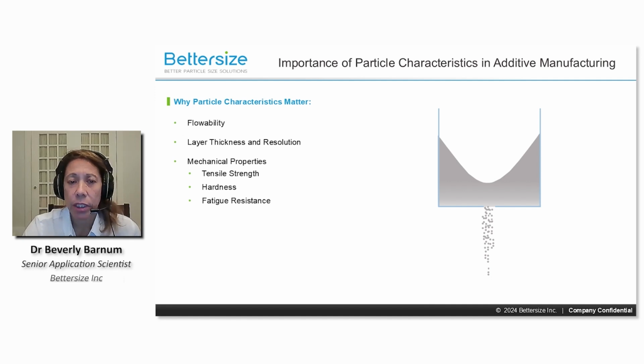And fatigue resistance is the property of a material that allows it to resist breaking down over time under the influence of changing workloads. Additive manufacturing parts are typically less resistant to fatigue than conventionally fabricated parts, but this can be overcome. Additive manufacturing parts can have defects like lack of fusion, gas pores, surface roughness, and grain boundaries that can make them less resistant to fatigue. And the material microstructures, including its grain size and phase distribution, affect the fatigue resistance. Smaller grains can better absorb and dissipate energy from loading, while certain phases can reduce crack propagation.